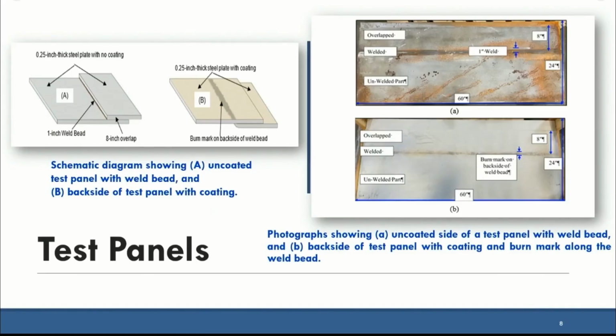First of all, I would like to tell you that we have used test panels which were cut from an actual tank plate, which were brought from the field, and they were welded. But before welding, of course, they applied the coating to the other side, which is the side which is going to face the soil of the tank. The actual plate was about 120 inch by 60 inch, and the overlap area of the welding was 8 inches. For ease of transportation, we got 60 by 60 inches, and we cut the test panel from the actual application in the field because we want to see what's happening in the field. We don't want to have it under ideal conditions.